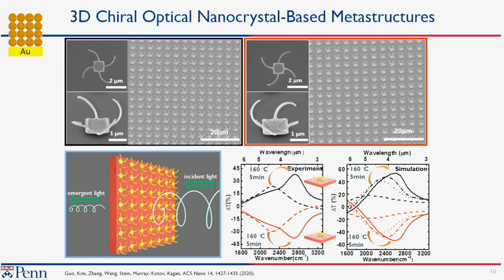The example was, could we use this as a way to create chiral metamaterials? And so what we did is we got a little smarter and put gold as the metal underneath, which creates much better adhesion, and so it creates much more uniform processes and strain. But you could print the two-dimensional structure of the pinwheel in one, concave, whichever way you like to think, pointing left, pointing right.